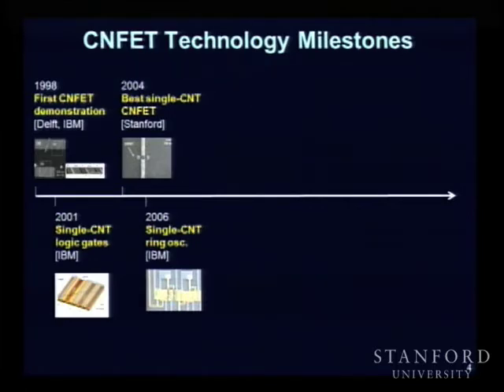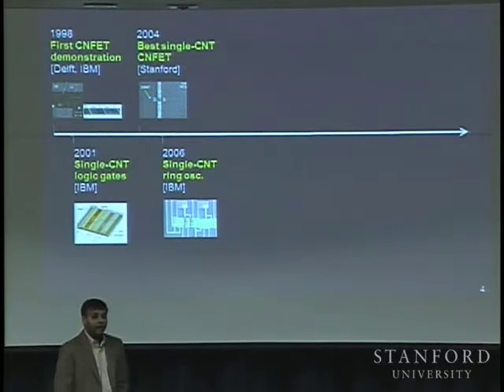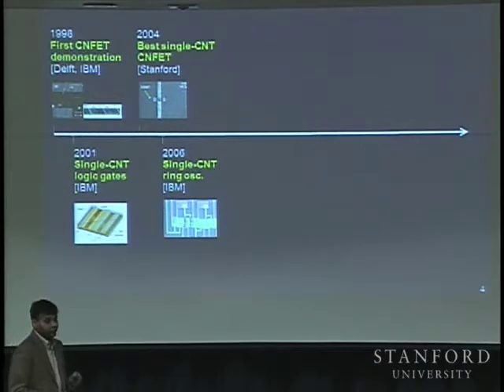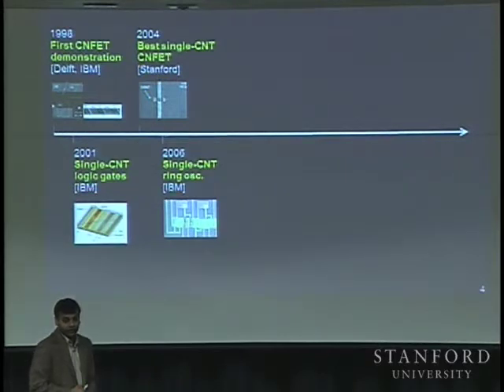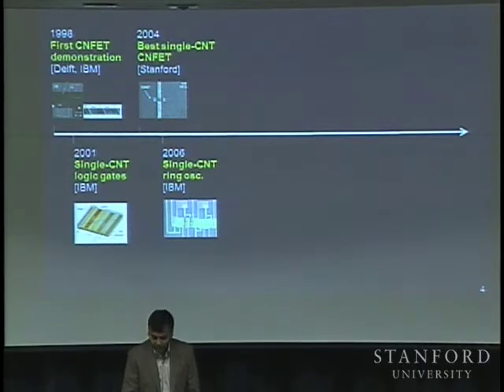Now, these are very significant scientific achievements, because without the foundations that have been laid by these people, some of the work that we have been able to achieve would be nowhere. Okay. So in 2004, that's the record on the best single carbon nanotube CNFET. This was done at Stanford by Professor Hongjie Dai in the chemistry department. And in 2006, this is a very famous paper, many of you are familiar with this one, where IBM showed a ring oscillator out of a carbon nanotube. What they did was that they had a substrate that had a lot of carbon nanotubes. They found a particular carbon nanotube that was useful for them because this was a semiconducting nanotube, and they built a ring oscillator on that semiconducting nanotube. These are very important scientific achievements.